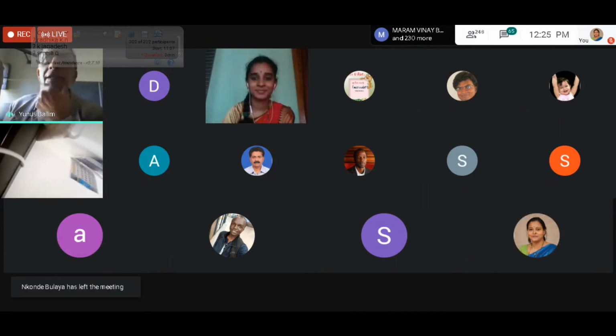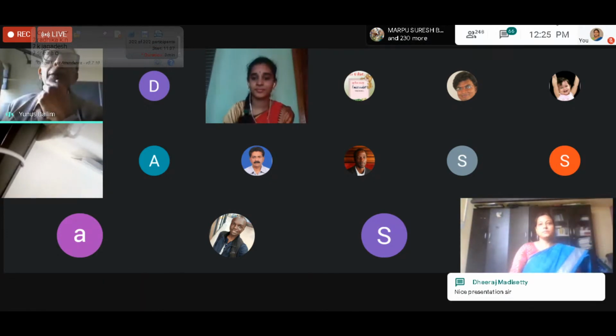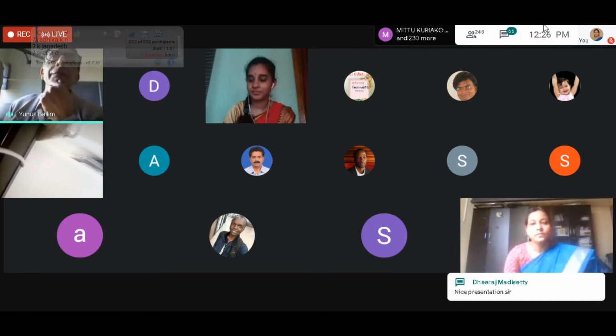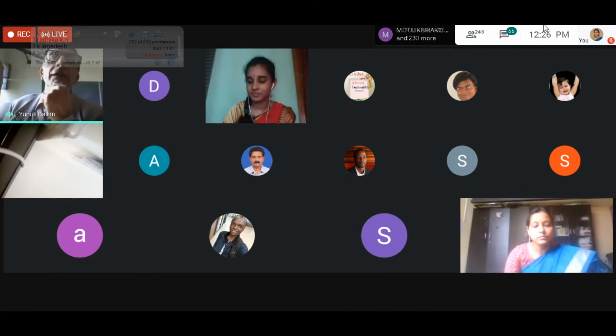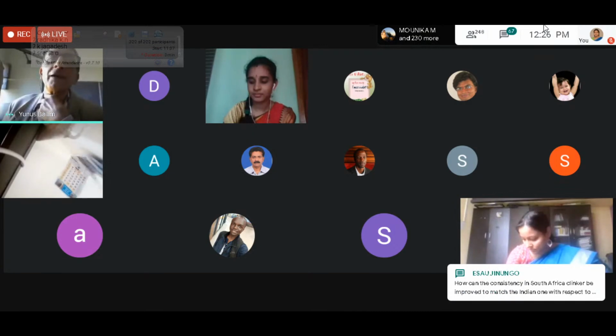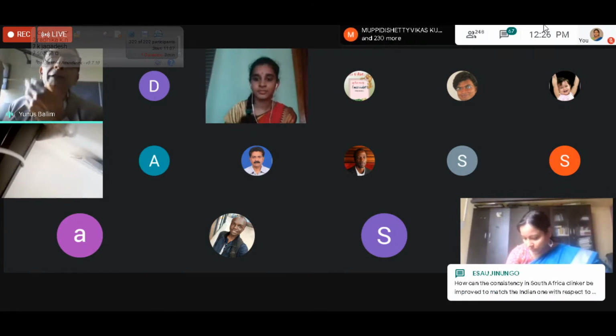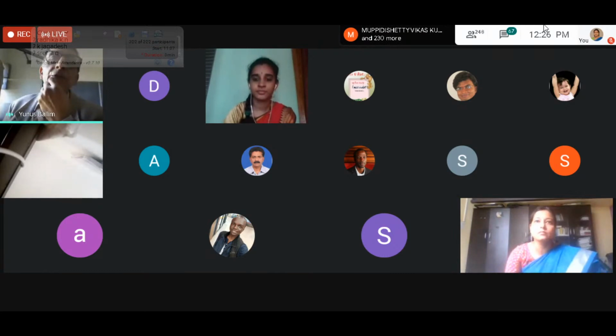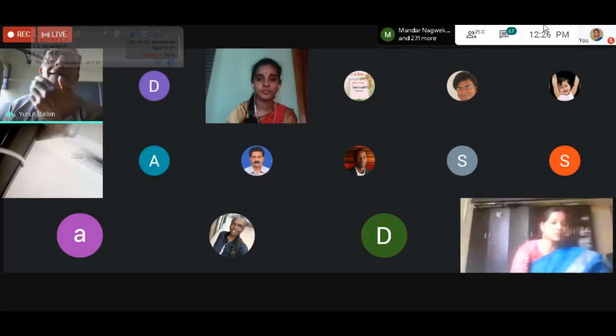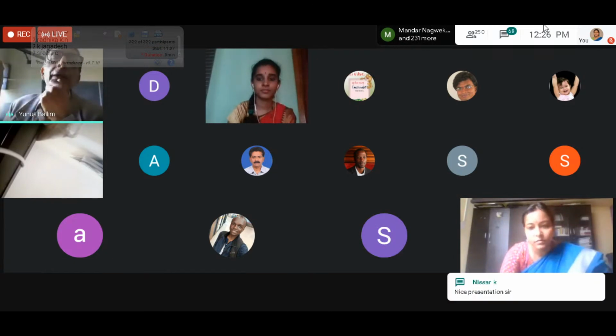What we did was we did normalize to 20 degrees C. But you don't actually have to normalize to 20 degrees C. You could choose any other temperature depending on the conditions. If you happen to use an isothermal calorimeter, you would set your calorimeter to whatever room temperature you choose. I think the one that our colleagues use in South Africa is about 25 degrees C. But it doesn't really matter. All you're looking for is a normalized heat rate function at a particular temperature.